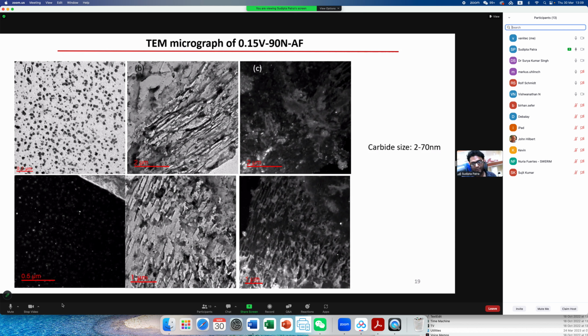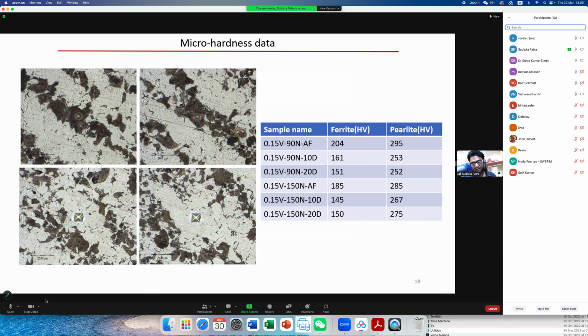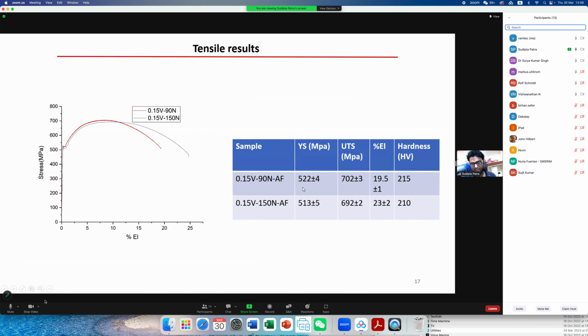That is why I want to make another steel with 0.1 vanadium and vary the nitrogen also. Then we'll observe, and also do the TEM study, even checking the samples twice. We have made 3 tensile samples, and there we got this result consistently, with no variation. We are getting between 520 to 525 in this range only, for the yield strength. Okay, but we will be looking into this in detail.